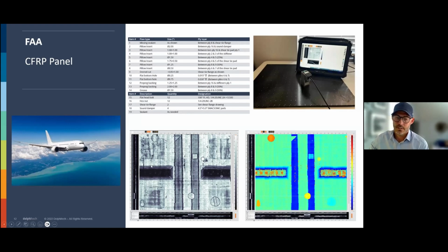And then you can see here on the left side is the amplitude image, which I showed you, which is more similar to X-ray, if you will. And then you have time of flight, which is the depth information here on the right. And you can see the stringers here in blue. You can see that there's a little bit coming loose from the stringer, between the stringer and the carbon fiber, which is glued to the carbon fiber. And you can see if there is some contamination inside the part.